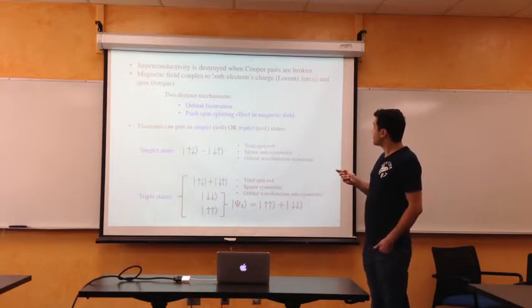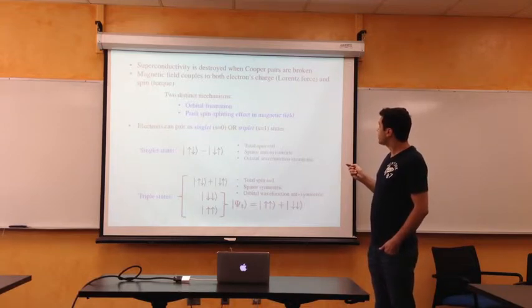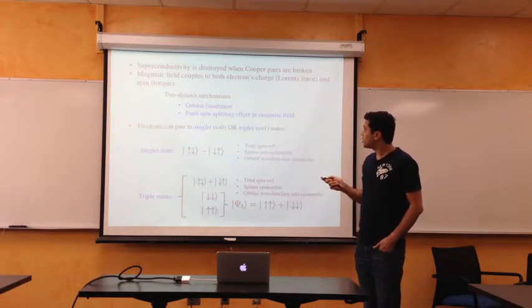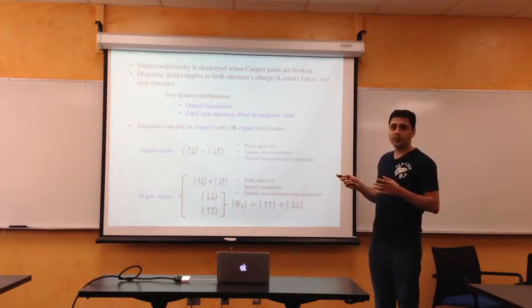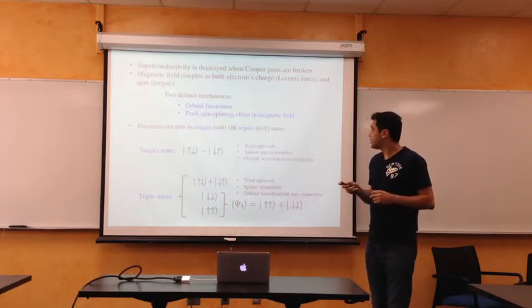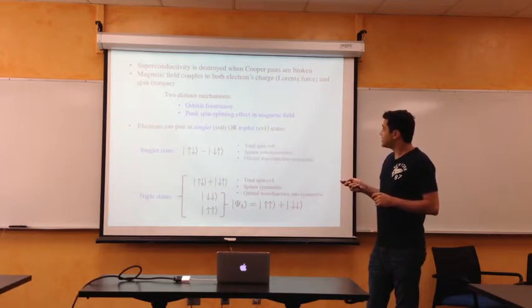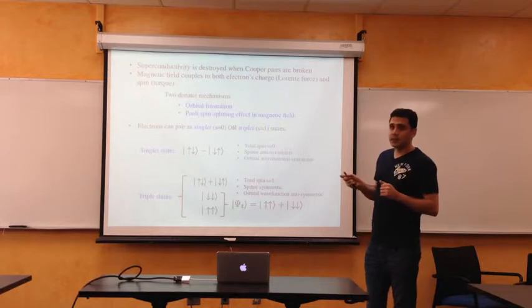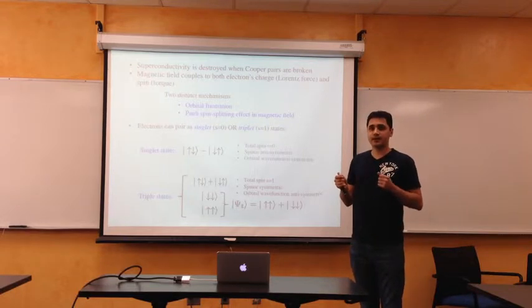So in the first case, the case of the Lorentz force, we can think about the destruction coming about through the orbital frustration of the order parameter. And in the second case, the spin-splitting effect is due to the fact that the magnetic field tries to align the spins of the Cooper pairs.